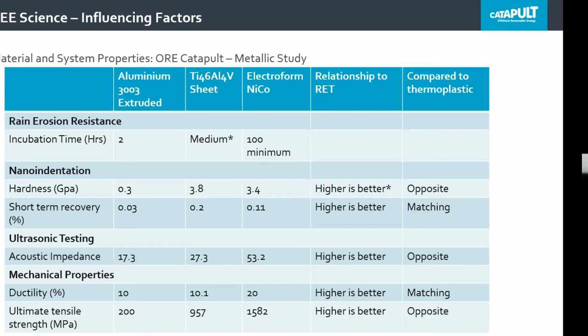And if we do the same looking at nano indentation, what we see is the opposite, that actually for hardness, higher is better. Short-term recovery actually matches that with the thermoplastic materials. Interestingly, in metallics it is better to have a high acoustic impedance, which was opposite to thermoplastics, and better ductility, and actually higher tensile strength, which is also opposite.